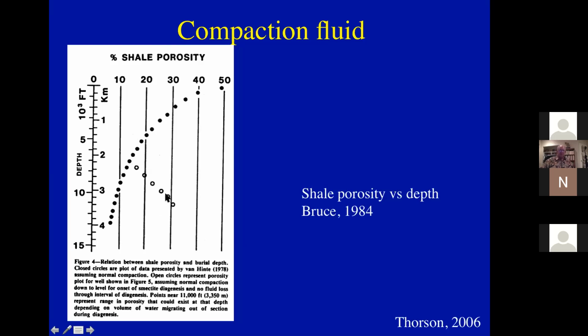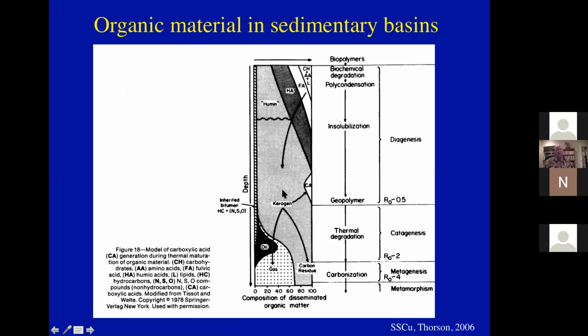The pores in these shales are being inflated by extra water. We'll get back to that in a minute. At that same depth in the sedimentary basins, you have the generation of hydrocarbons. Generally, 3 kilometers depth, generally around 100 degrees centigrade.